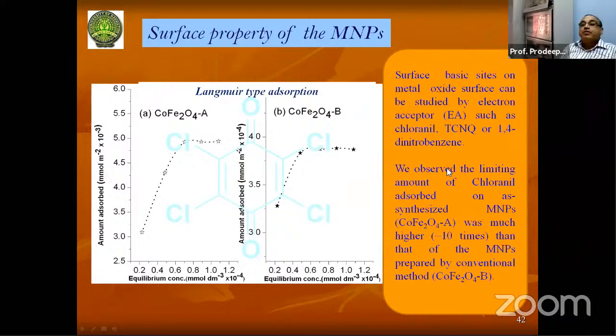Okay, and we observed a limiting amount of chloranil. So this is the chloranil absorbed on the as-synthesized one, A, which was much higher than that on MNP prepared by the conventional process. So this is the conventional way. We have synthesized magnetic cobalt ferrite nanoparticles, which are already known in the literature, using some capping agents, and here we have used the ultrasonic method. So you can see here their surface properties are much better, meaning the surface polarity looks very high. It's because they absorbed more chloranil on the surface of the magnetic nanoparticle.